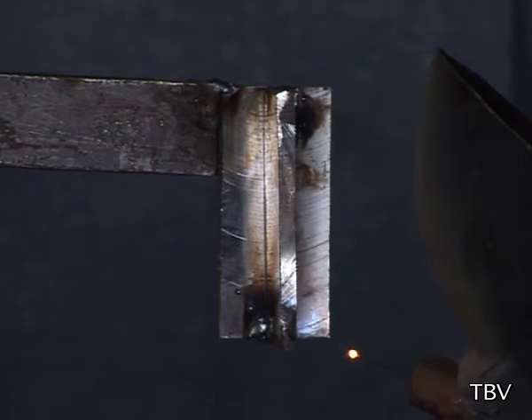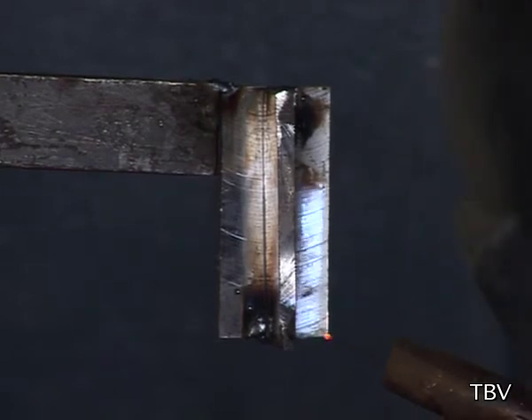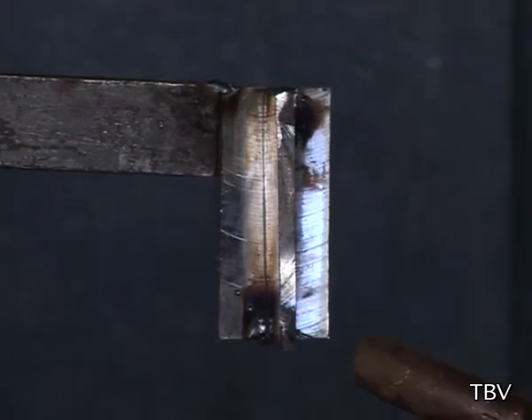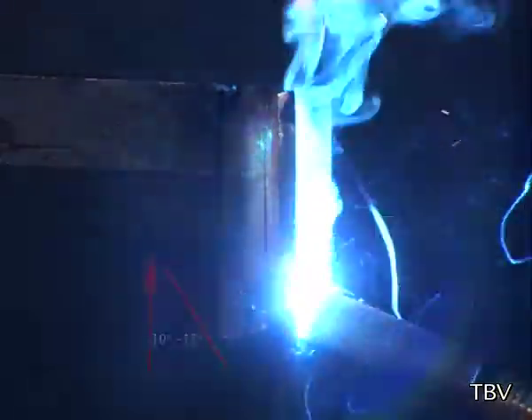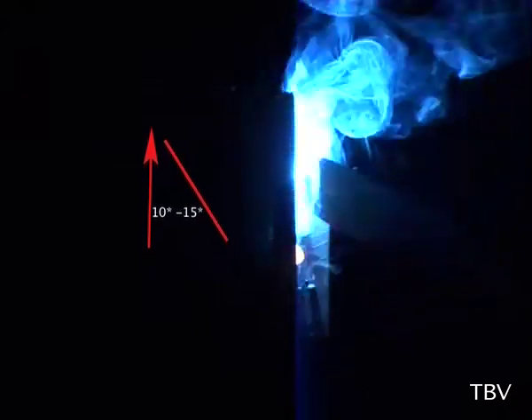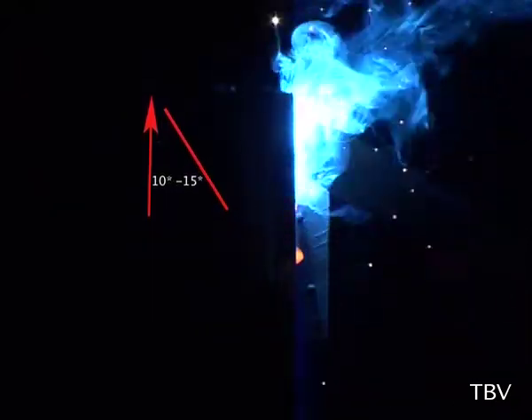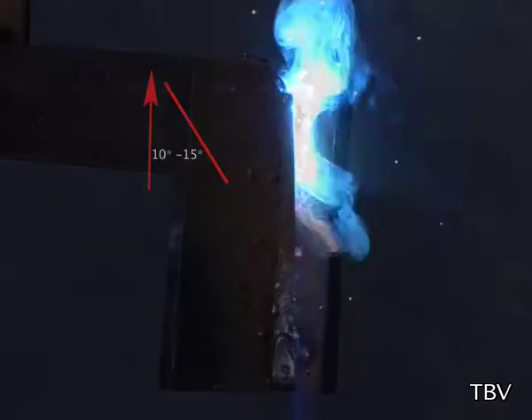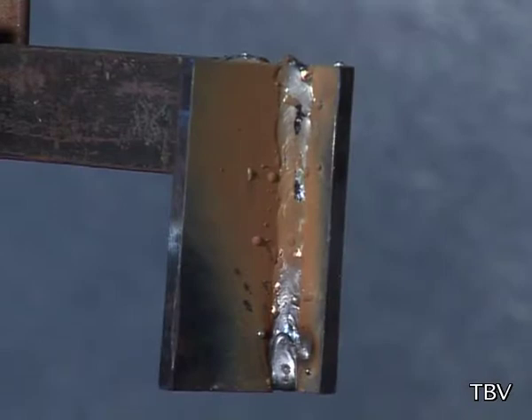Open the carbon dioxide gas flow before striking the arc. Strike the arc maintaining a filler wire stick out of 8 to 10 mm from the end of the contact tip to the job as required for dip transfer mode. Weld to the full length of the workpiece by filling the material in the weld area, moving upward in forward movement. Allow it to cool.